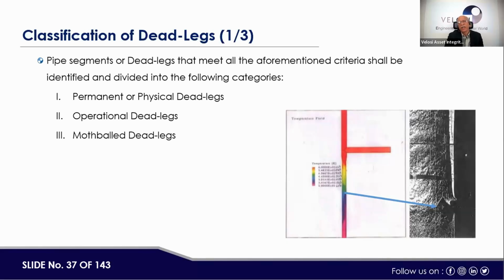Then mothballed dead legs are the dead legs where, if one portion of the plant is not kept in operation for any reason, and a part of the plant is kept out of service for a certain period, months or a year, then it may have high internal corrosion if it was not cleaned properly, not purged, and not mothballed. So when you put it back in operation, it can give some surprises. So mothballed dead legs are also required to be taken care of properly.